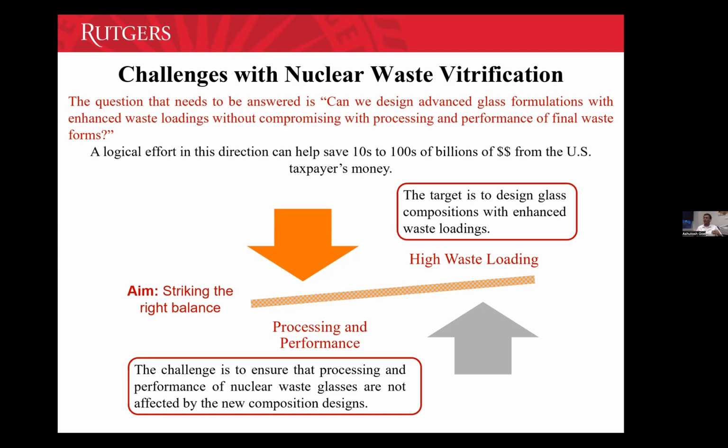So the logical question in this effort is, can we increase the amount of waste that we put into the glass? Let's say 100 grams of glass today contains 40 grams of waste, and there are 60 grams of other components that we add from our side. Can we somehow increase the waste loading, increase that 40 grams to 60 grams, and still make a glass that is chemically durable and will not dissolve easily? If we can do that, that will be a huge thing, right? So we need to strike the right balance.